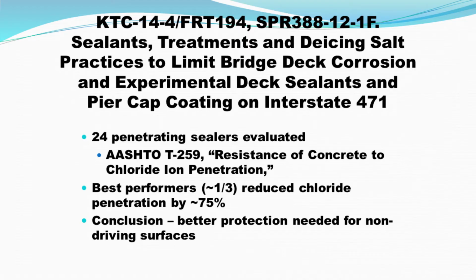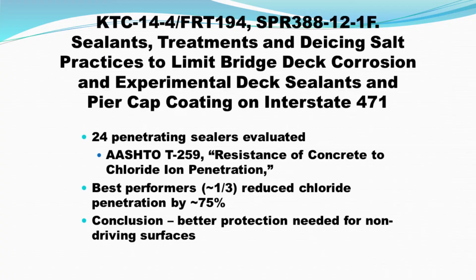So in the second study, after we did the study for identifying how bad the problem was, chloride ion penetration into our concrete structures, we looked at mitigation of that. What can you do to prevent further deterioration? What can you do to prevent further chloride ion penetration? The common thing at the time was penetrating sealers, silane, siloxane-based penetrating sealers. The University of Kentucky did a study where they evaluated 24 commercially available penetrating sealers, most of which were either silane or siloxane-based, ranging from 4 to 7% silane to 100% silanes.